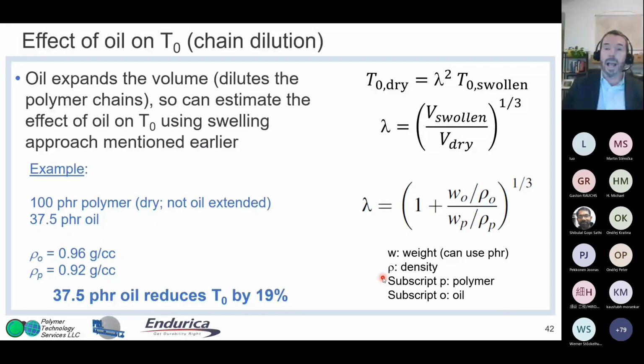Oil is a relatively simple thing to rationalize because, again, it's related to that swelling effect. If you add oil to the rubber formulation, it pumps up the volume and dilutes the polymer chain. So based on the swelling discussion I had earlier, you can determine a swelling ratio based on the amount of oil you're adding and the density of the oil relative to the polymer density. It's pretty typical to buy oil extended elastomers like SBR, and oftentimes they have 37.5 parts of oil. I was curious what would happen if you did this kind of analysis, and what you find is that oil extension reduces the fatigue threshold by almost 20%. So if you want a rubber compound with high durability and long lifetime, taking out oils and low molecular weight things is generally a good strategy.